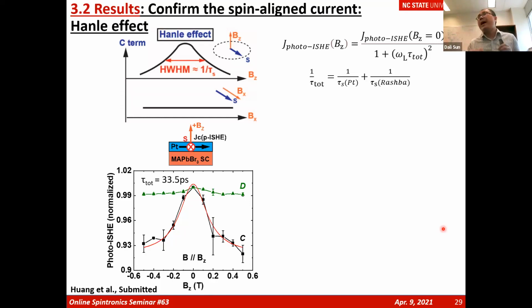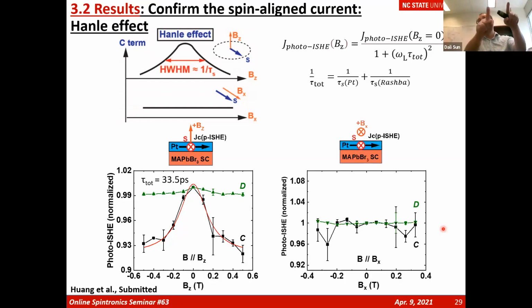The D component, that's the photocurrent background, has no spin information, showing a negligible magnetic field effect. There is still a little bit, due to the magnetic field effect from singlet-triplet interconversions, but that magnetic field effect is very small. But then we see a pronounced decay, the typical feature of the Hanle effect, with the C component, which is the circular-polarization-dependent component, showing a decay at high magnetic field. If you apply the magnetic field parallel to spin orientations, no change has been observed. So that really confirmed there is a spin-aligned photocurrent formed due to the circular light illumination due to the Rashba effect. Until now, we demonstrated, yes, there is a spin-dependent photocurrent.